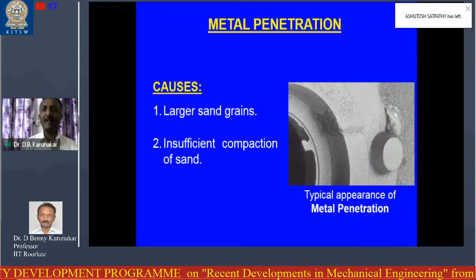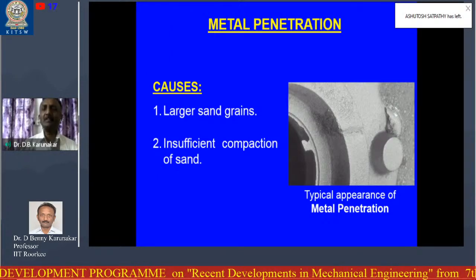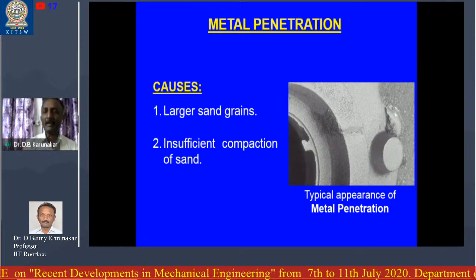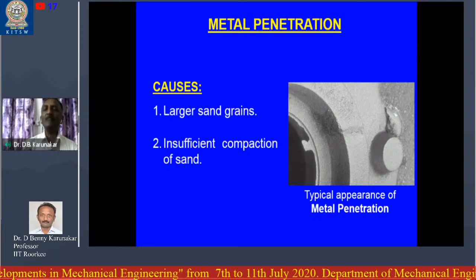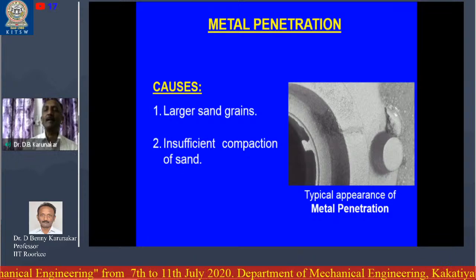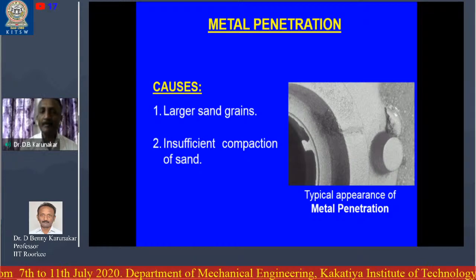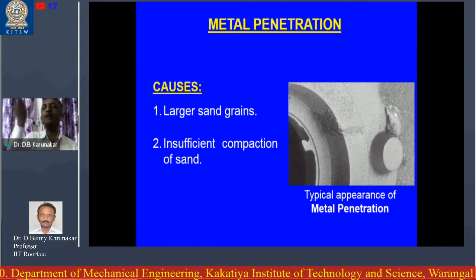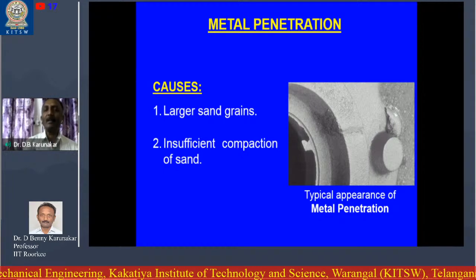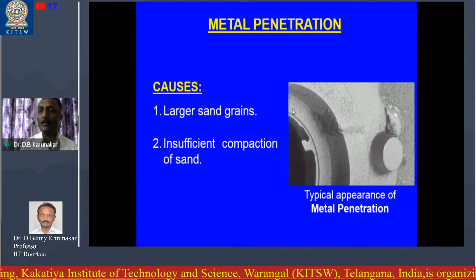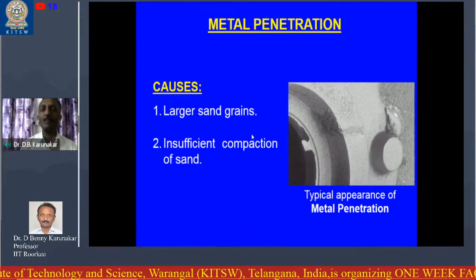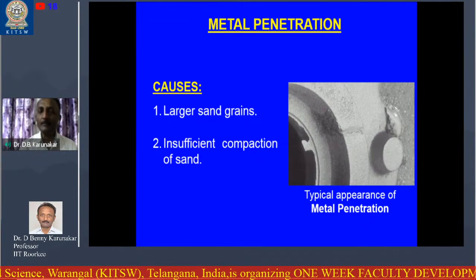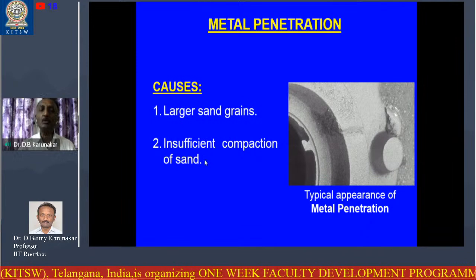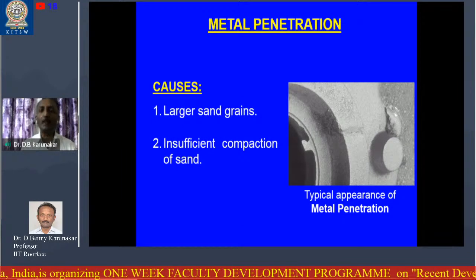The sand grains are so large that there is a significant gap between neighboring sand particles, and molten metal is able to penetrate into that gap. The molten metal penetrates into the molding sand, and the unwanted deposit is created on the surface of the casting. The same thing can happen due to insufficient compaction of the sand also.